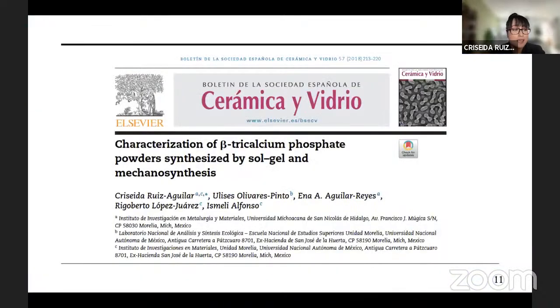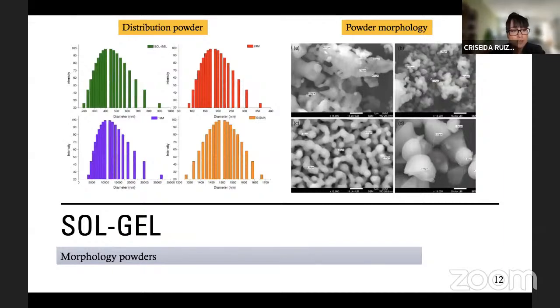Then I'm going to show some results of my research lines about calcium phosphate and bioactive glasses. In this article, a comparison was made between sol-gel and mechanosynthesis techniques to synthesize beta-tricalcium phosphate, and the results obtained allow us to understand the effect of the synthesis method and the particle size of the tricalcium phosphate powders. To conclude, the sol-gel particles were smaller than the mechanosynthesis ones, as you can see in this slide.